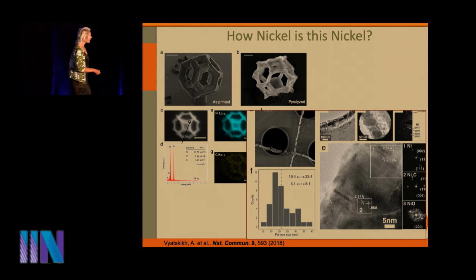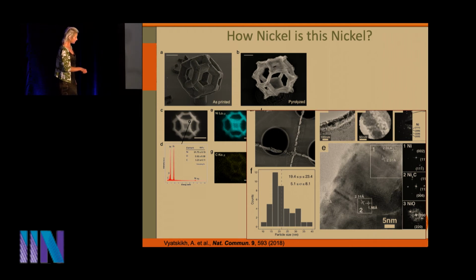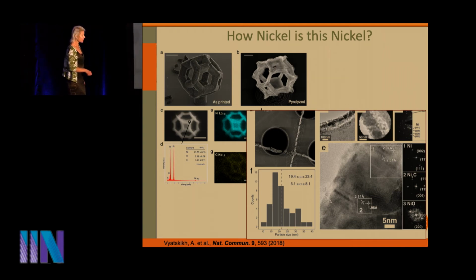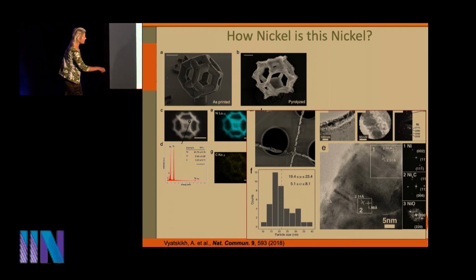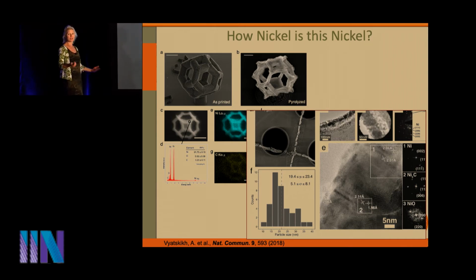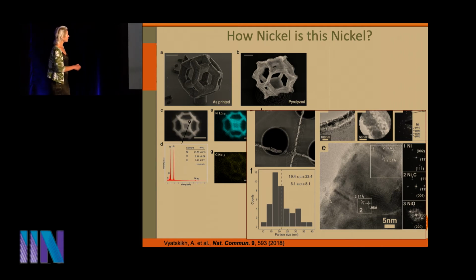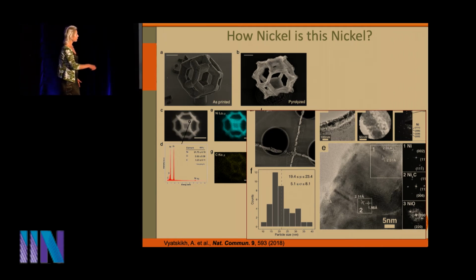And what we're learning right away is that, first of all, it's nanocrystalline. So the mean grain size here is about 20 nanometers, so 20 nanometer grained nanocrystalline nickel. We see that it's mostly nickel, so you can see this very clear diffraction pattern. We see a little bit of nickel carbide, and we also see some nickel oxide, which very likely formed just on the surface as a result of native oxide formation.